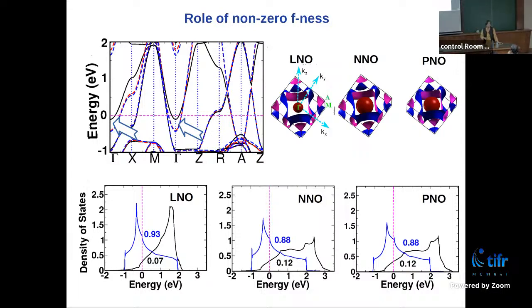Then that can be tested with other lanthanides. Very difficult to make this sample, and very few in the world have observed superconductivity, very few. So I was discussing with Rajdeep, he could not be here, so I discussed the whole thing with him. First of all, it is observed only in thin film. It is not observed in single crystal. No one has tried it in the single crystal of neodymium nickelate, but lanthanum nickelate infinite layer, people have tried a lot. They could not see it. But in the thin film, they could see it. What about gadolinium? For gadolinium, I don't think there is any experiment, but even if you do gadolinium, my bet will be, it won't change much.